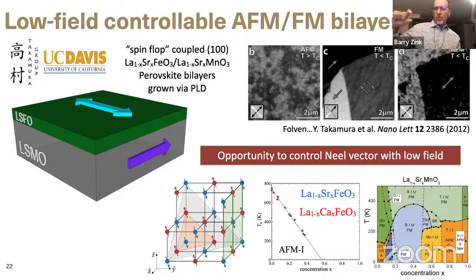And so she had that material, and then she put a thinner, nominally insulating antiferromagnet on top of that. That's lanthanum strontium ferrite. In the regime that she was studying, with this relatively thin lanthanum strontium ferrite and the exact doping that she picked, she got something really cool to happen. This is shown in these PEEM images taken at the synchrotron at the ALS. You can see that the magnetization vector of the LSMO points in one direction, which is of course controllable with an external magnetic field. But the Néel vector of the LSFO on top of it is always arranged at a 90-degree angle to the magnetization of the LSMO.